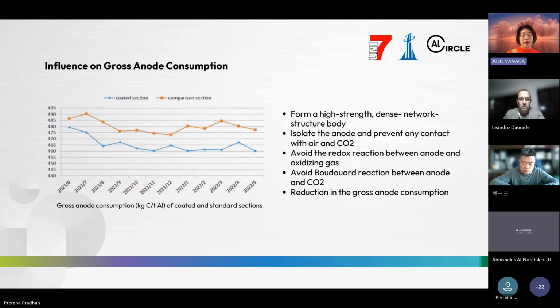The fourth, the significant reduction in gross anode consumption. So we say GAC. Anode consumption is another major raw material cost for smelters. And our coating delivers one of the most impressive benefits here, a drastic reduction in gross anode consumption. How does it happen? The high strength, dense network structure sintered body acts as a perfect barrier, like an armor, isolating the carbon anodes from air and CO2 in the pot.